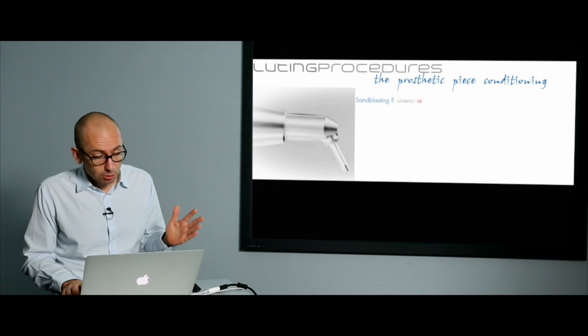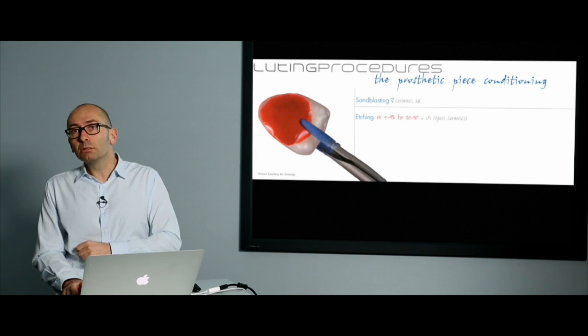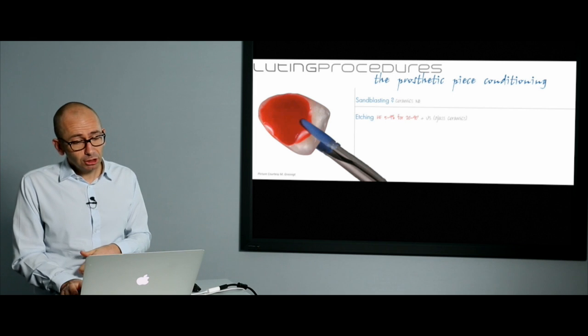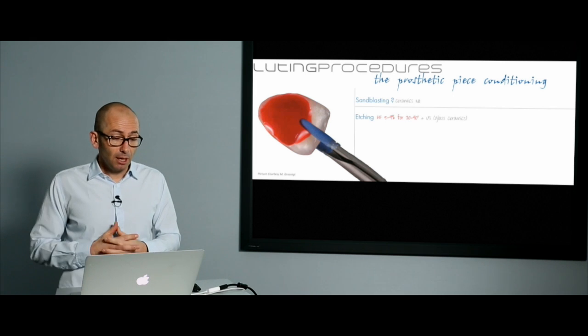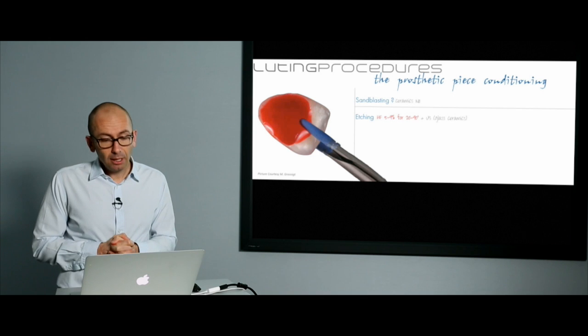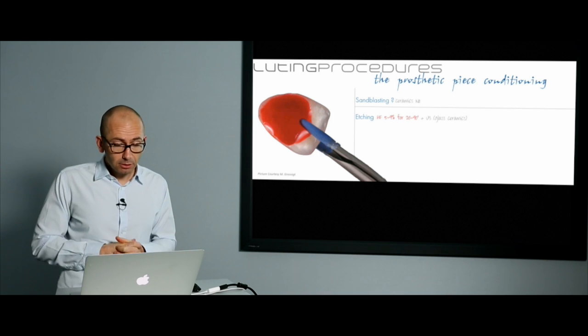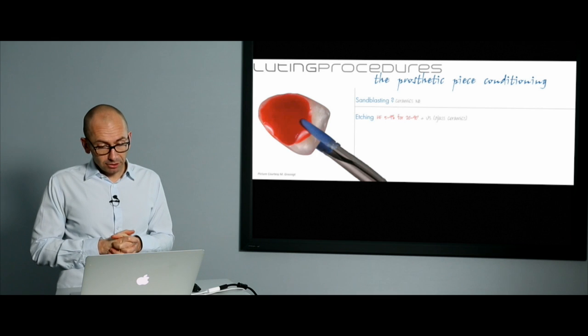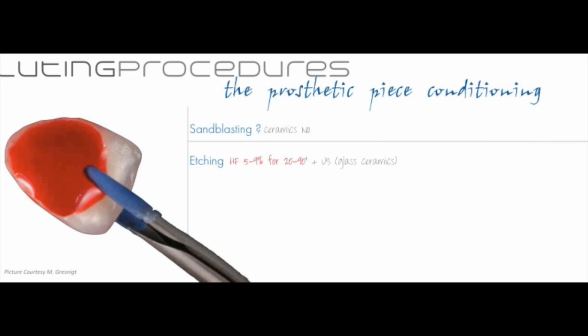So to prepare the surface and to make it rough, it's a better idea to use some acid. And especially, you've got a special one for the glass ceramic, which is the hydrofluoric acid. Different concentration depending on the ceramic you're using, between 5 and 9% concentration, and the time that you will etch it also depends on the ceramic you are using. So just take a look at what the manufacturer is recommending, and for example, for disilicate, it's about 20 seconds with a 5% hydrofluoric acid, and for feldspathic, it's about 90 seconds of etching with a 9% hydrofluoric acid, depends.